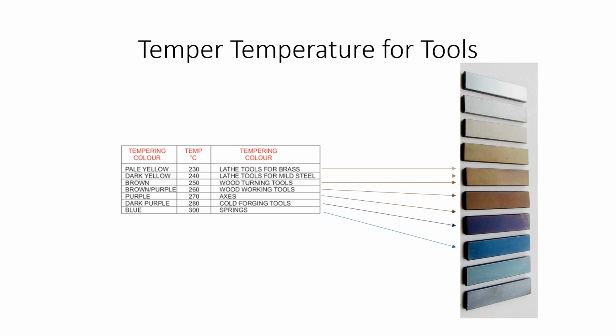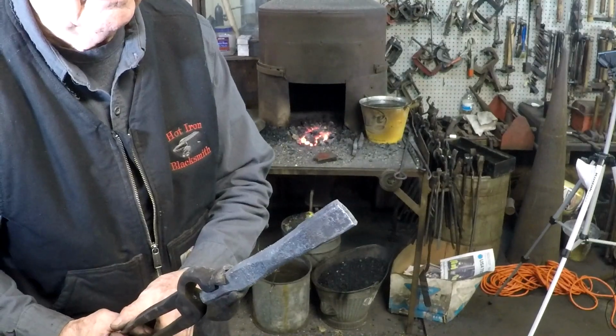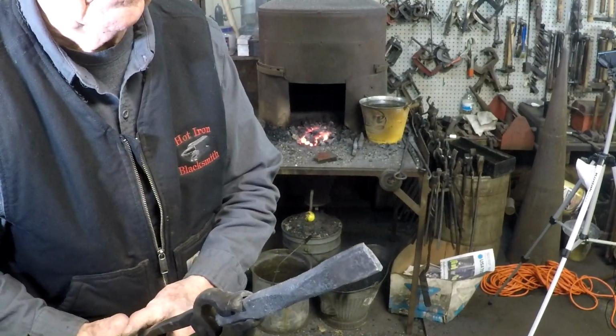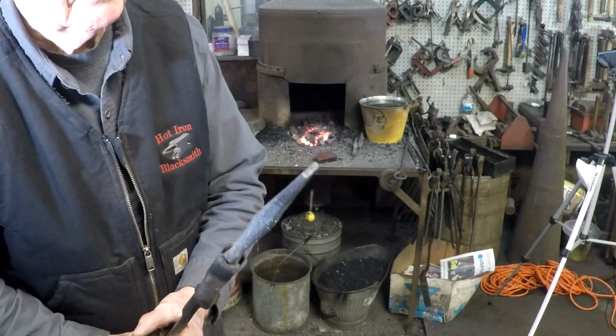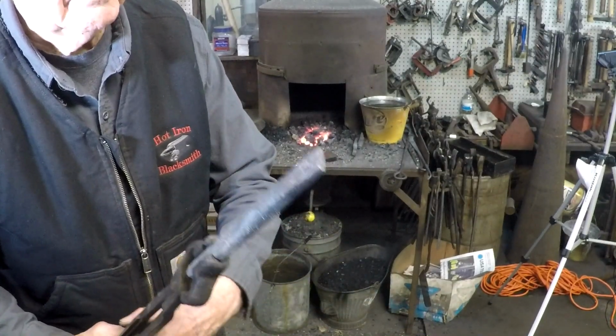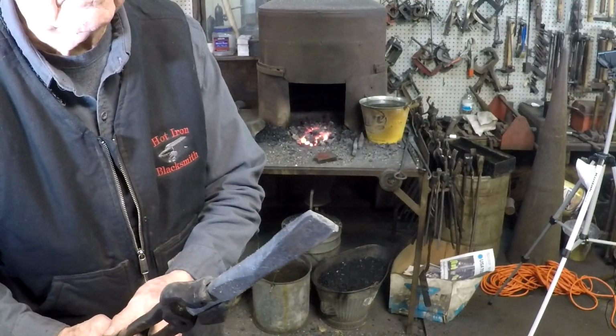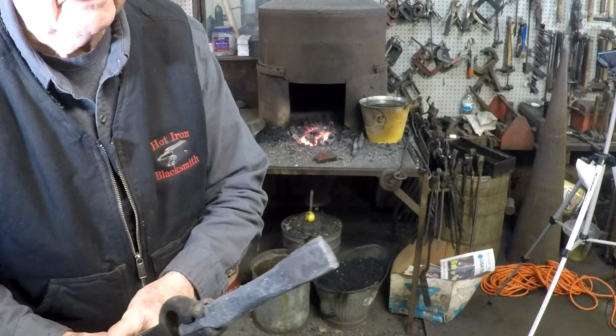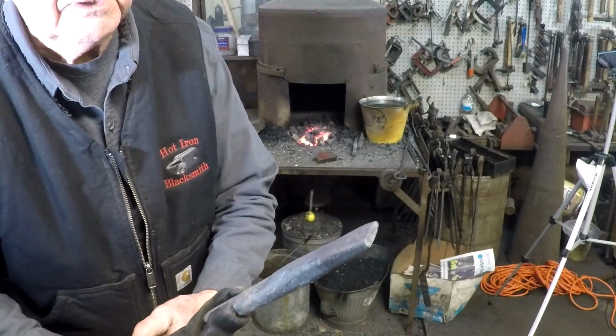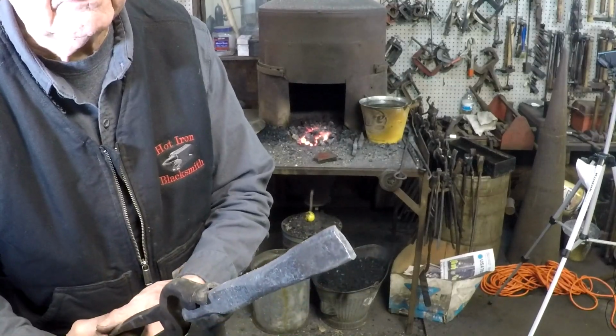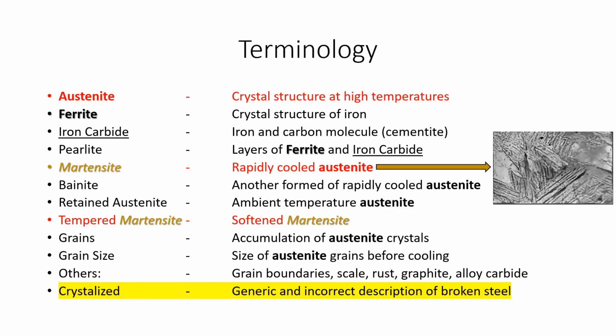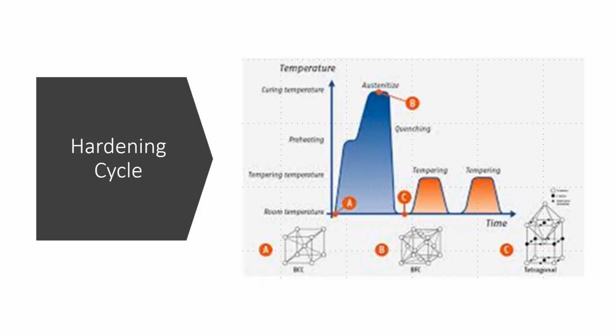This second reheat is not absolutely required, but it's really nice to do that. And technically the reason is that in the first process of quenching into the water bucket, there was about 30% of the steel that did not convert into the hardened form, and it's called retained austenite. When we reheat within the tempering process, it allows the retained austenite to transform, and then our second process that we're doing now is tempering that remaining 30%.